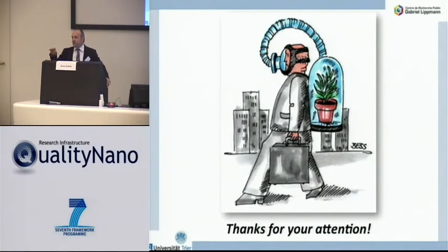You will use phosphor, it will show you where your nuclei are. And then you can choose the other 2 or 3 channels from the mass detectors for your silver particle, for example. And then you would exactly see where the silver is and how big the particles are within the resolution of the equipment. That's what we plan to do.